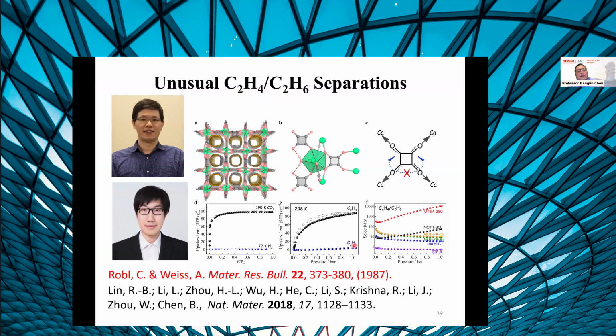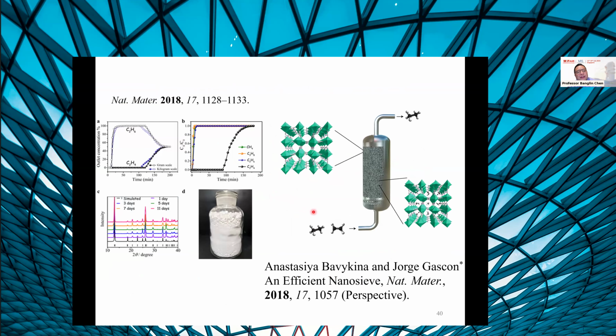And I would like to thank the reviewer, who pointed out that this is because of the rigidity of the framework, and the squaric acid there's a limitation for rotation which fixes this framework and makes this framework rigid. Furthermore, that material is very stable in water because it can be synthesized in water, and also can be synthesized by chemistry, and so in large scale, and this is a very promising material for true gas separations. This work was highlighted by Bavykina and Gascon in Nature Materials.